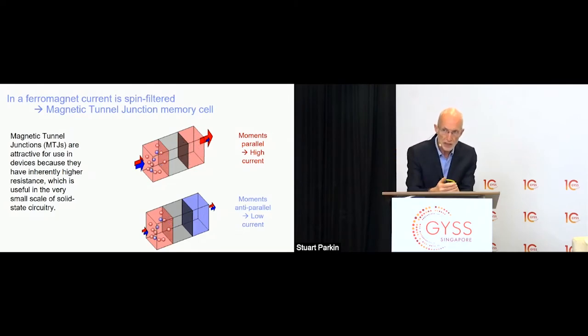The opposing magnetic layer, if it has the same magnetic orientation as the first one, can accept those electrons. There are empty states of the same spin polarization into which those electrons can tunnel. The tunneling process itself is ultra fast, and the spin orientation of the electron is preserved. However, if we change the orientation of that second moment, as shown in the bottom cartoon, so it's now in the blue direction, you can essentially switch off the current, because now there are no longer many states of the polarization of the tunneling electron. And so there are no states into which it can tunnel, and the tunneling current is reduced.